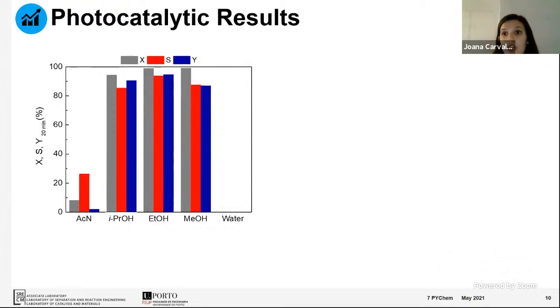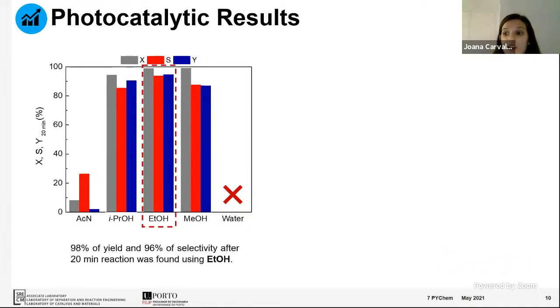During the reactions, samples were taken and analyzed by HPLC, and the results are presented in this graph in three different parameters: conversion, selectivity, and yield after 20 minutes of reaction. When water is used as a solvent, I don't see the formation of furfuryl alcohol. When acetonitrile was used as solvent, the production of furfuryl alcohol is very low. When alcohol was used as solvent, the photocatalytic activity is much higher, and ethanol is the best option for the solvent.